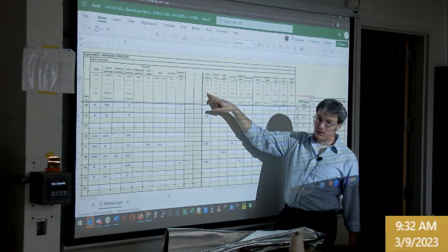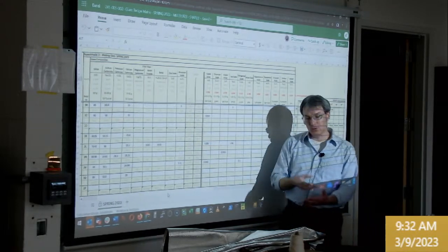Then you take this amount of cobalt oxide, which is 78.6% cobalt, and the remainder is oxygen. You take this mass times 0.786, and then divide that mass of metal by the batch weight, and that tells you the percent of ion in that final batch that's responsible for the color we'll see.